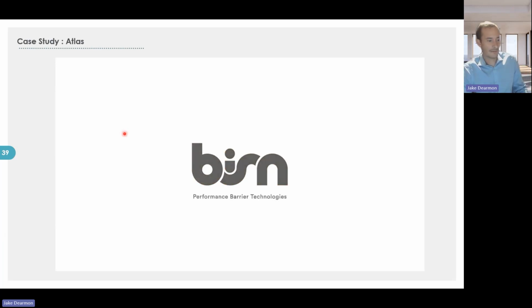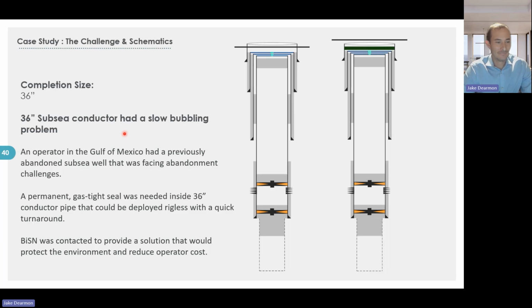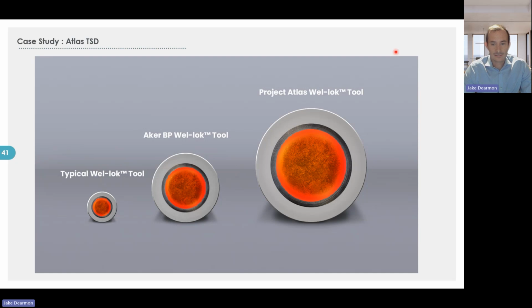So that explains it a little bit better than I could. But here again, this is the schematic of that. So we had a couple of feet to work with above the mud line. There were some 20-inch P&A caps on top of the existing 20-inch in there. And really the only way to address this problem, cement couldn't do it just because there was not the length, unless you brought a rig in to be able to circulate clean fluid over. The only real option was a BiSN plug up here in the very top, which is what we were able to do. Give you guys a quick overview.